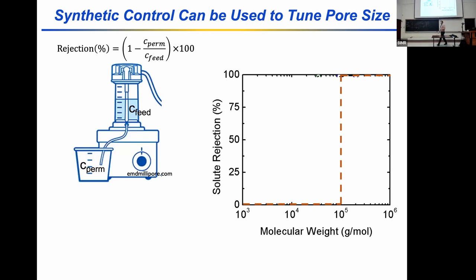The exciting thing for me, as someone interested in membrane science and membrane transport, is that when we take these two membranes and test them in a solute rejection test or a molecular weight cutoff test, you can see this change in pore size percolate through to the membrane properties. The experiments on this slide take a feed solution with different molecular weight PEO samples dissolved in it, and put the membrane right under the feed solution. Then we try to pass the feed solution through the membrane and collect the permeate, right? If the PEO molecules are too big to make it through the pores of the membrane, they end up getting rejected and their concentration is reduced. When we report that as a percent rejection, they'll have a relatively high percent rejection because they didn't get through.